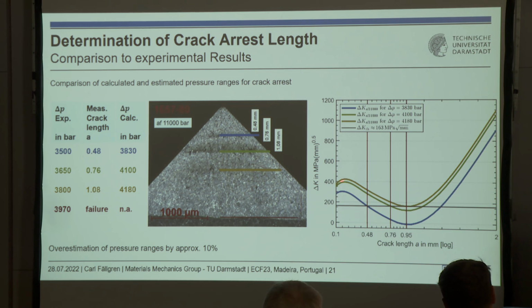when the stress intensity factor range drops below the delta K_th value, there should be a crack arrest. So for the blue line, which I compared to the experimental results, I calculated an endurable pressure range of 3,830 bars, and it was actually 3,500, and I calculated it for the same measured crack length. So you see the overestimation of pressure ranges which are endurable for these kinds of specimens was only approximately 10%, which I'm pretty happy over.